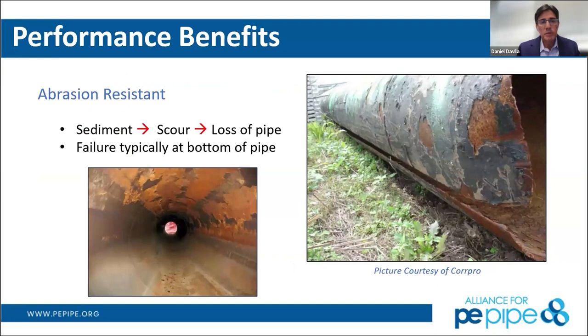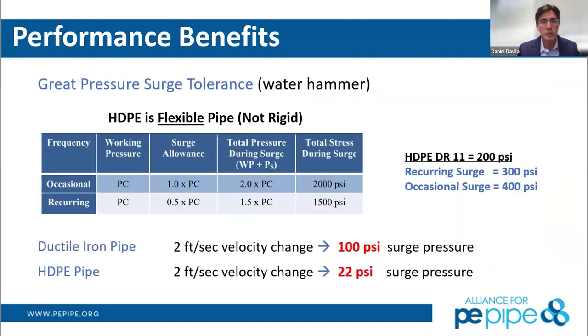Another benefit of using this pipe is that all pipes, whether it's gravity or pressure pipe, have some sediments. And with sediments, there's a scouring at the bottom, and there's eventually loss of material. As you will see on the picture, this pipe failed at the bottom. So this also is a benefit of the HDPE latest resins. Let's talk about water hammer or pressure surges. There's great tolerance because HDPE is flexible. Everybody has experienced water hammer when you're in an old building, maybe in a hotel, you shut down the faucet too quick and you hear the bang on the walls. That's essentially the water being stopped instantaneously, and it hasn't dissipated the energy. So the energy needs to go somewhere. It's usually absorbed by the pipeline. Because HDPE is flexible as opposed to being rigid, it has the capability of absorbing this.